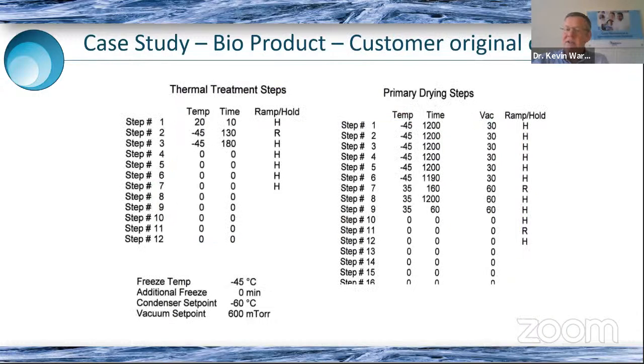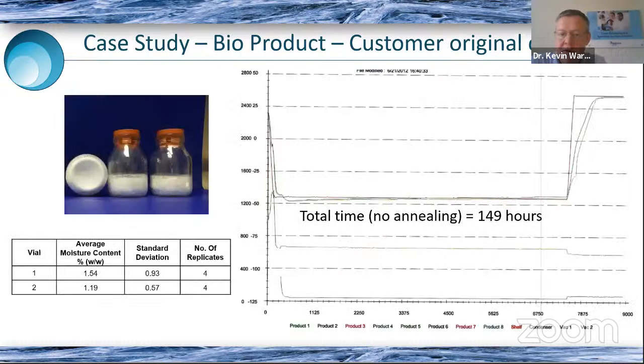And then when we looked at the customer's original cycle, you can see that in order to make sure that they can guarantee to keep the product below -40, they'd used a shelf temperature of -45 quite consistently throughout primary drying, as well as in freezing. But you can see here there's lots of 20-hour steps. These 1200-minute steps here on the right, they're all 20-hour steps. So that actually resulted in a freeze-drying cycle that was 149 hours.